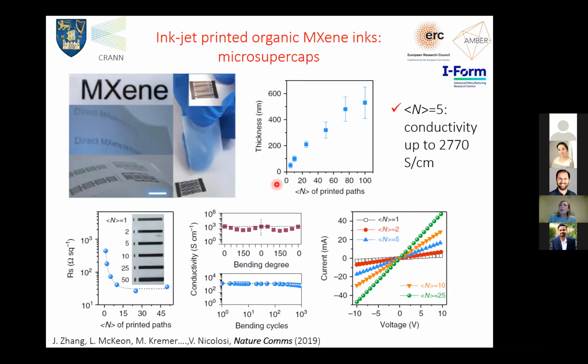And we saw that in this case you are not limited to making only one pass, like for the stamping method, but we could print many layers and build the thickness of our device. The beautiful thing is that if you track the conductivity, we realized that by printing only 5 passes, we could already achieve an extremely high conductivity. We reached about 3000 Siemens per centimeter, which was really, really good for the application we were seeking. And in this case, you could also see that the conductivity was not really affected by bending. So our devices have very high flexibility, and the conductivity was perfectly retained.